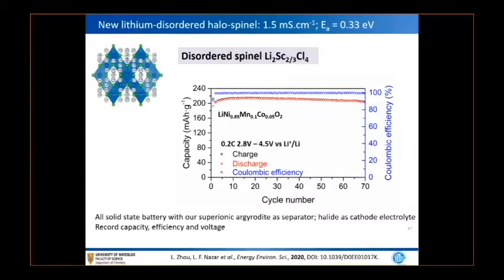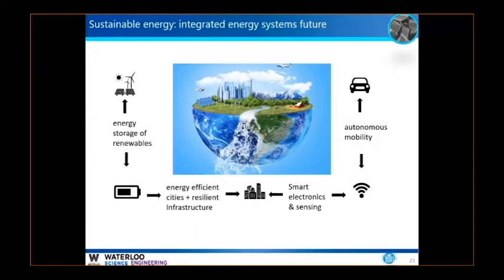And we have, this is probably a record now. This was just published in 2020, of a solid-state battery using a new type of halo spinel, where we're achieving 200 milliamp hours per gram. And this is only over 70 cycles, but this is obviously very recent data. So this is using that other material I told you about as a separator and these new coating-free cathode materials as the electrolyte.